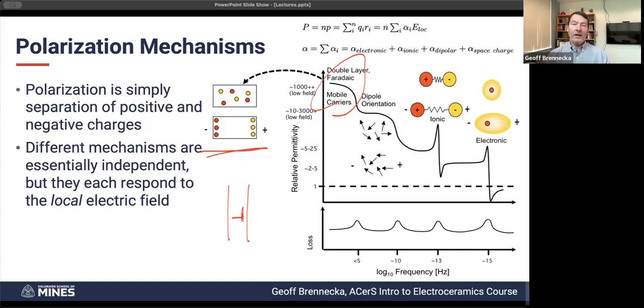So there are a whole class of capacitors that are built on this idea of having conductive grains and insulating grain boundaries. So you've got a lot of free carriers within the grain that you apply a field and they all fly over and run into the grain boundary and hang out there. And then you apply a field in the other direction and they all run over and pile up at the next grain boundary and hang out there. Those are great for storing a very large amount of charge at low voltages.